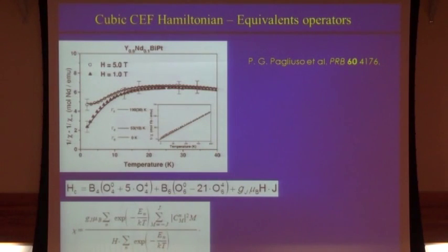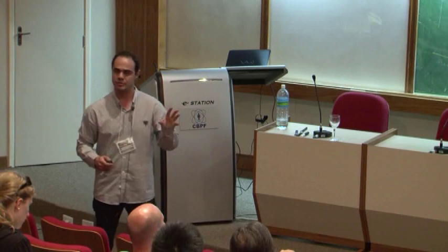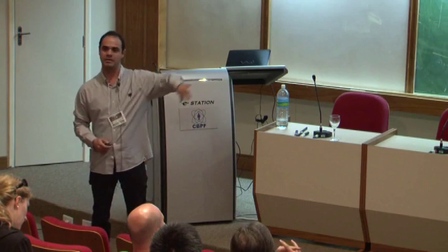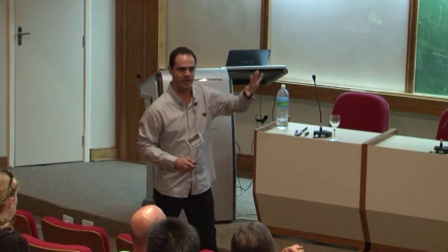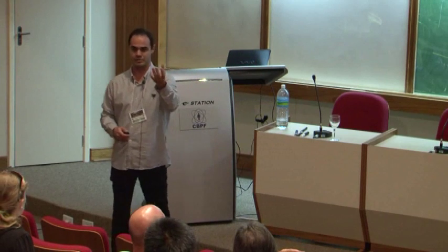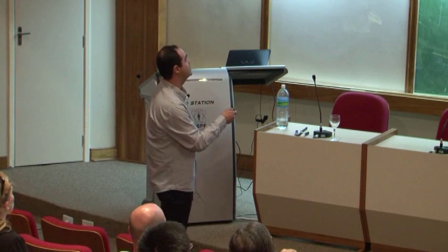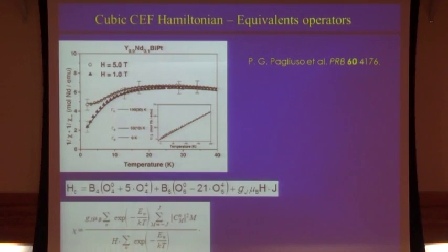It can also affect your magnetic susceptibility for the same reason, right? At high temperature, even for a paramagnetic material, you have your rare earth there, you calculate the magnetic susceptibility, right? It's a paramagnetic ion. But your Curie constant is going to change as a function of temperature, right? Because you are depopulating the levels. So you can see departures from a linear Curie-Weiss behavior in the inverse of the magnetic susceptibility. So you can see small departures here that you can fit, right?